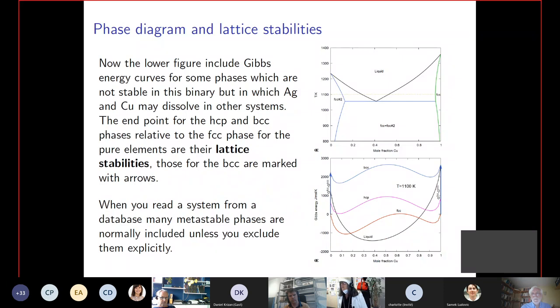And then, of course, there are other problems. You go to higher order systems. You may have elements which have other phases which are stable, like BCC or HCP or BCT structures, and when you want to mix them, you need to have the difference for each pure element. You need to have the difference in Gibbs energy between the different structures, and those are called lattice stabilities, and they are included in the database. So when you want to calculate, you will have to see the preference for the different elements in the different phases. And when you change composition and temperature, all of this changes. So this is what you minimize when calculating the diagrams.